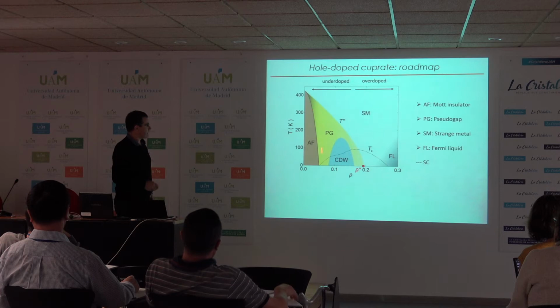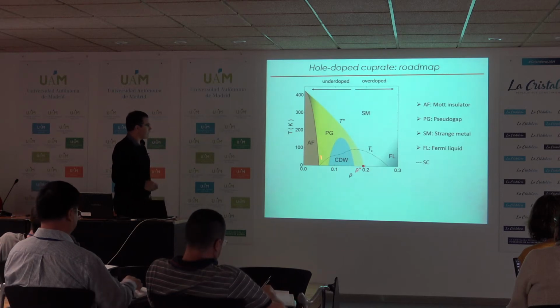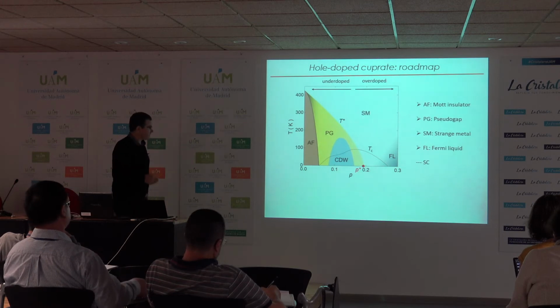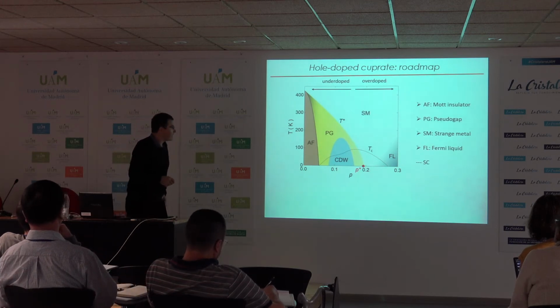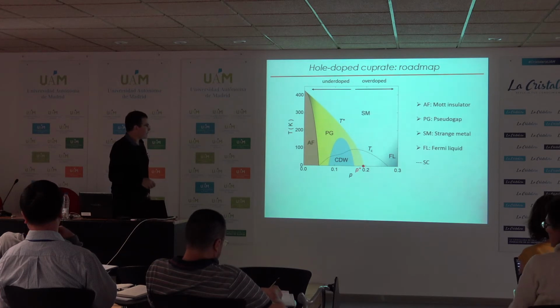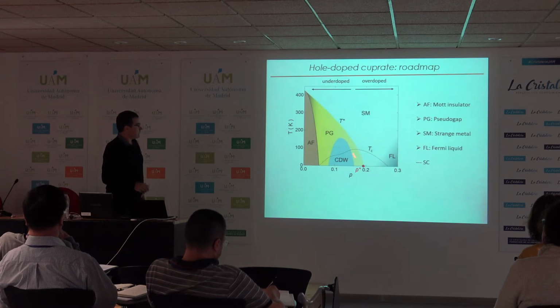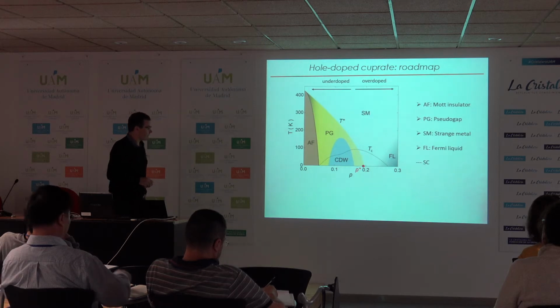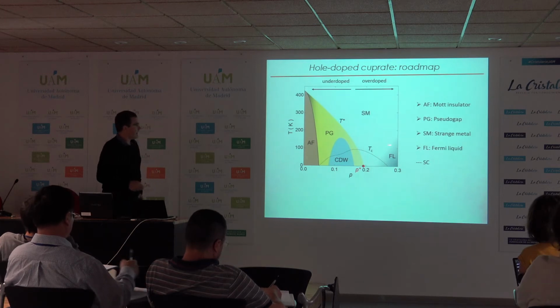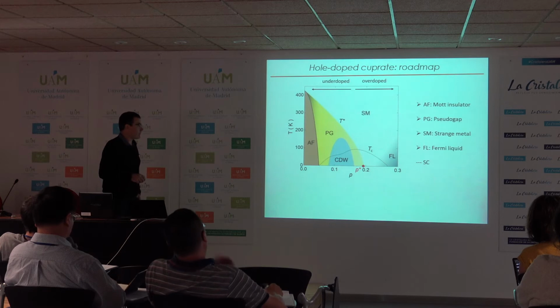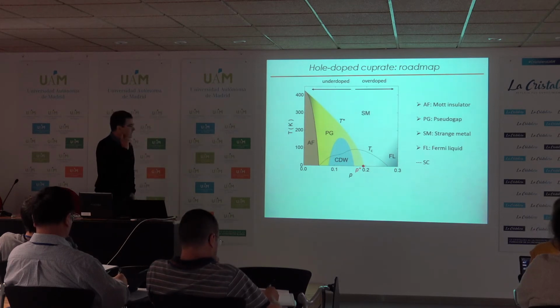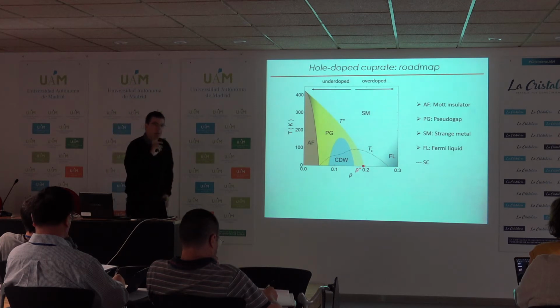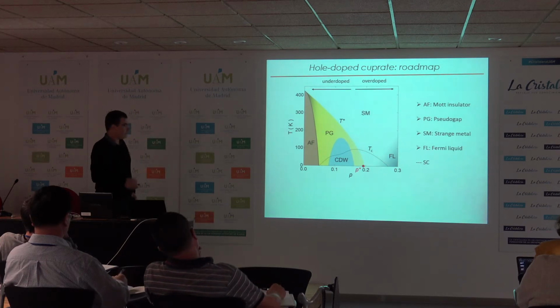As I have discussed, the parent compound is a Mott insulator, but this state is rapidly destabilized as you dope the compound. For YBCO at 5%, this state disappears, and then the superconducting dome emerges, here in dashed line. In yellow you have the famous pseudogap phase. Inside it is the charge density wave phase that I will discuss, and in the strongly overdoped side you have the so-called Fermi liquid phase. And I am going now to discuss some results obtained by transport property measurements in the different phases.